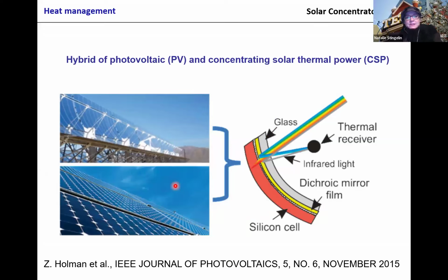Besides buildings and greenhouses, this is important for solar cells. One big problem of commercial solar cells like silicon solar cells is when they heat up, which they do because they have to be in the sun, they actually lose performance. So what people did at Arizona State University with these commercial solar cells, they put a heat mirror on top of the solar cell, shooting the infrared back to a thermal receiver, which they can use for solar thermal power, while letting the visible light through, so you could run the solar cell to create electricity from the visible light.